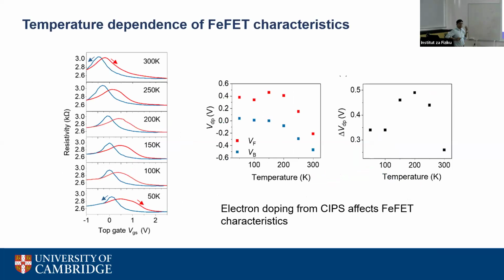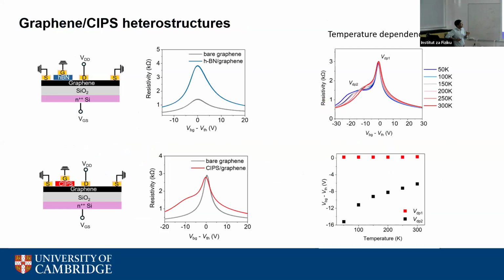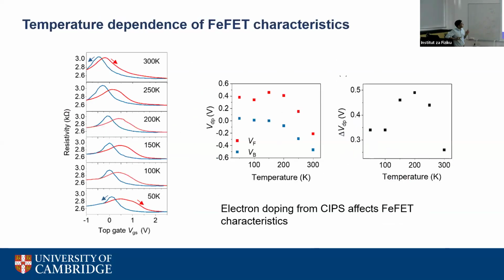As I said, the ferroelectricity is strongly correlated with the ionic conduction. And when we do temperature dependence on the ferroelectric FET, we can clearly see that the loop changes shape dramatically. You can see at 50 Kelvin, the loops are very asymmetric. Often people measure such loops at room temperature as well, and they don't understand this. And here, through a systematic study of the CIPS characteristics as a function of temperature, where it is known how the copper ion migration takes place, we show that as you increase the temperature, the loops become more symmetric because now the doping is not localized, as we show here. It is more delocalized, and you can make the entire channel n-type, which is reflected because both these Dirac peaks now move towards negative voltages, which suggests electron doping in the system.